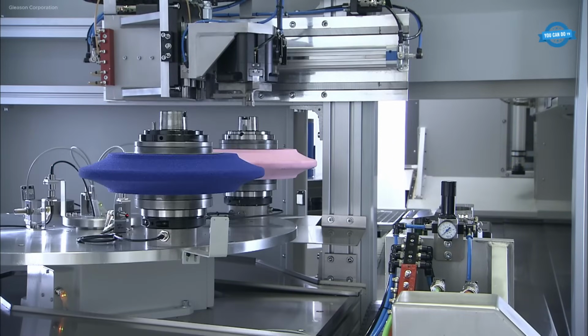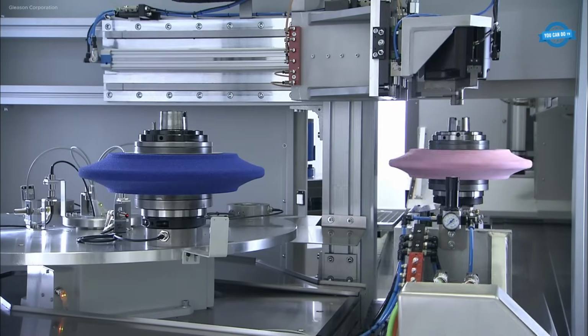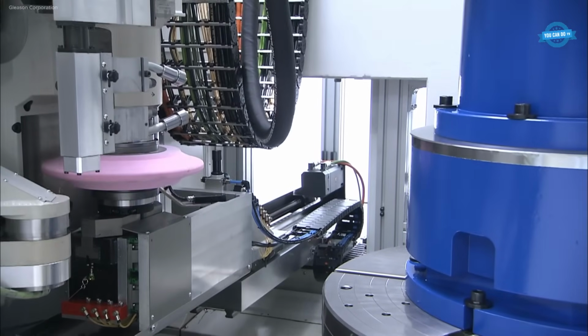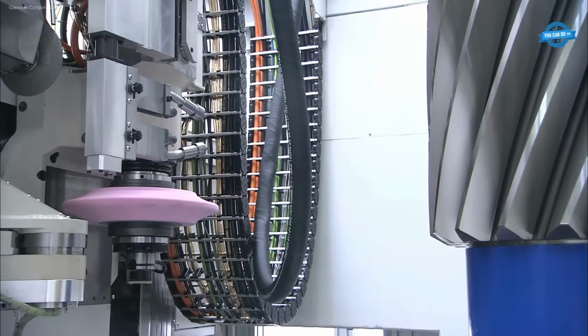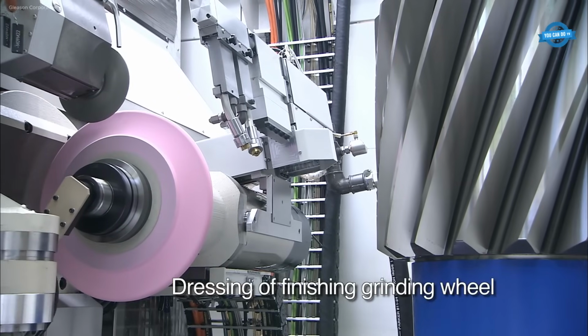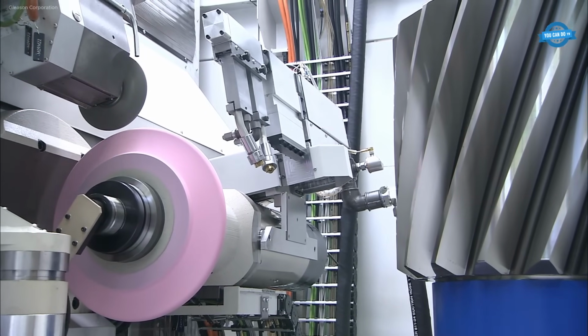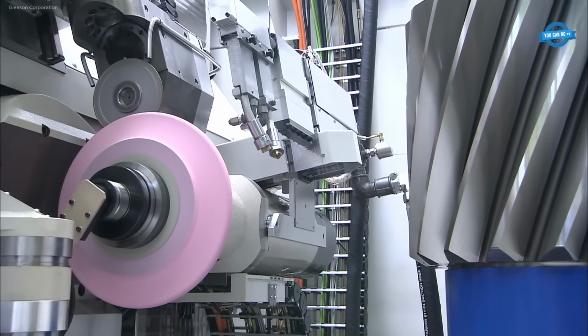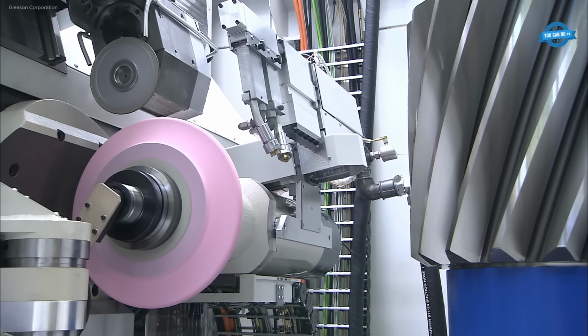Roughing follows with a coarse grit profile wheel for large gears, achieving 30% time savings. Finishing is performed with a fine grit wheel to reach surface finishes below RA 0.2, suitable for modules up to 44, ensuring the highest precision and quality.